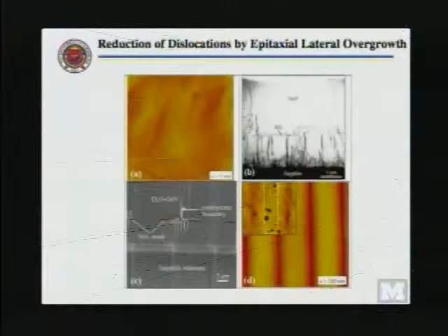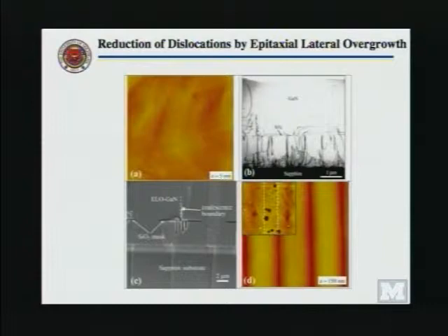Remember, gallium nitride is not like silicon. It doesn't have a nice substrate, so you have to deal with disorder. These are highly disordered things. So we explore different methods of reducing these dislocations. We grow on patterned substrates, and we are semi-successful. In some cases, we can reduce them. But at the end, the dislocations are in a way related to the efficiency of the light.